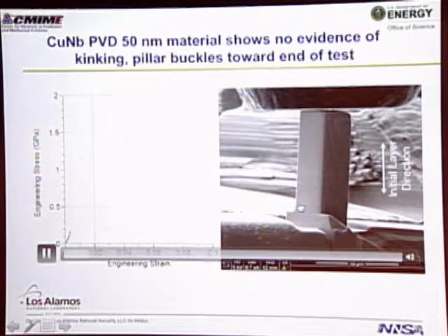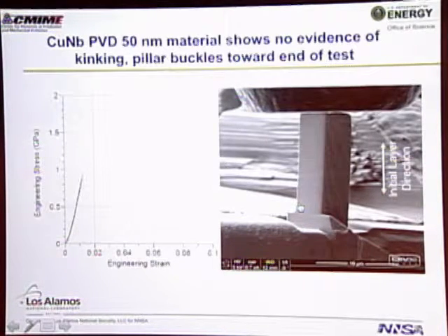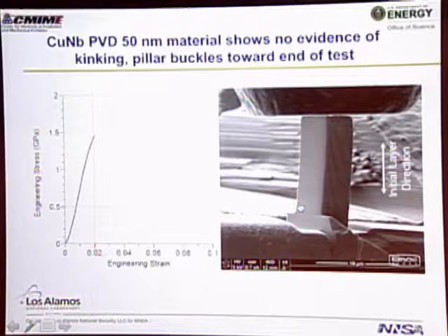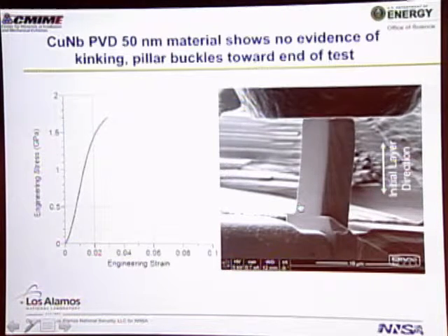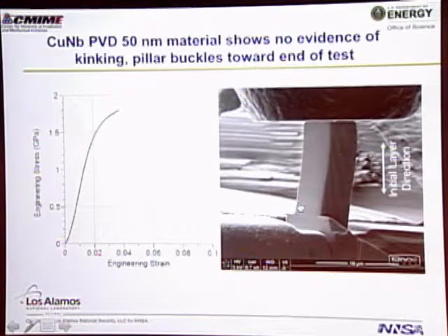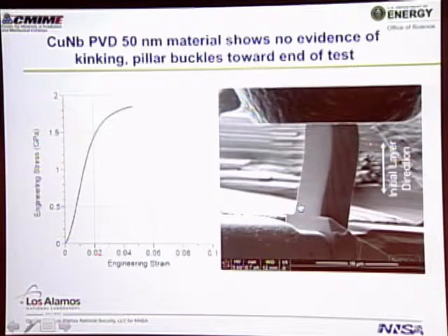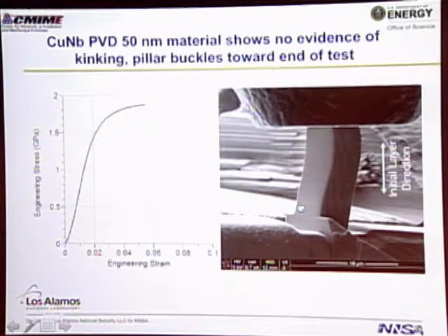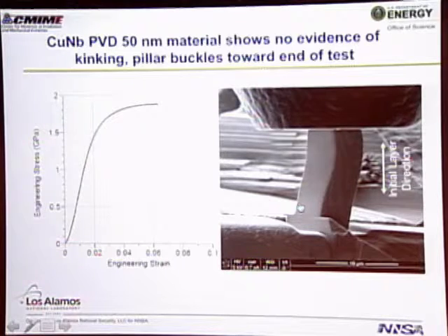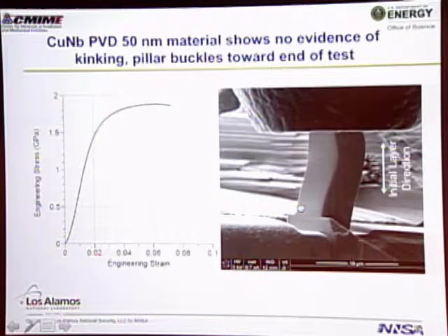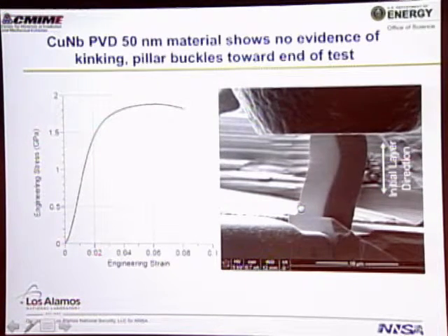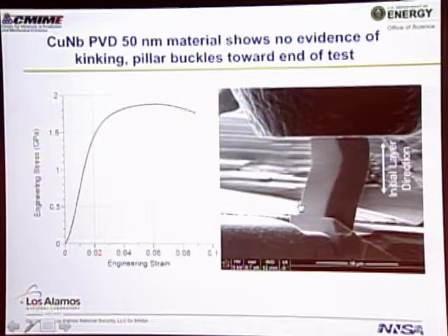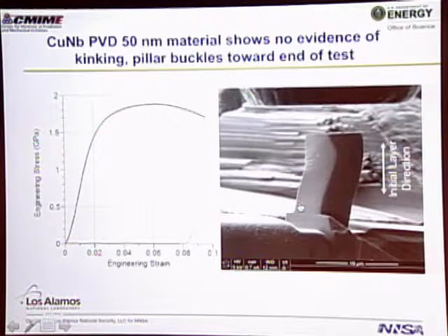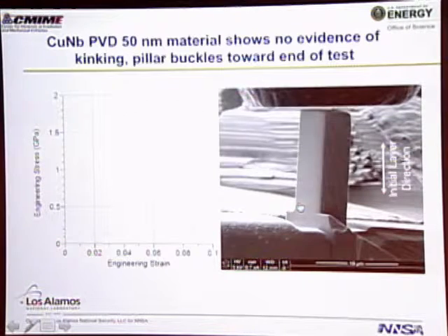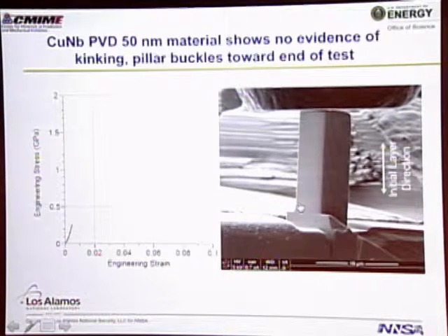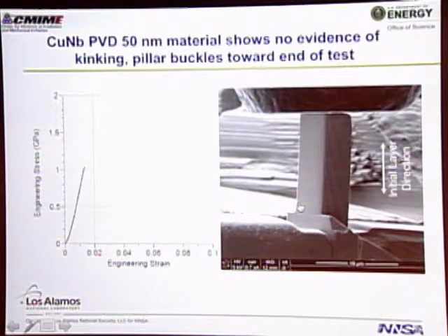So this is the physical vapor deposited material. You see that the material loads up, and then it starts to deform. That's when this curve starts bending over. You can see this guy starts kind of bending over a little bit. It hits a maximum strength, and then as it starts to bend, it gets a little bit softer. And then we unload it. So in this case, you don't see much on the surface of this material when we deform it.